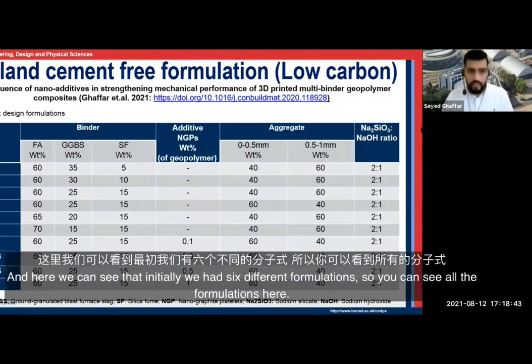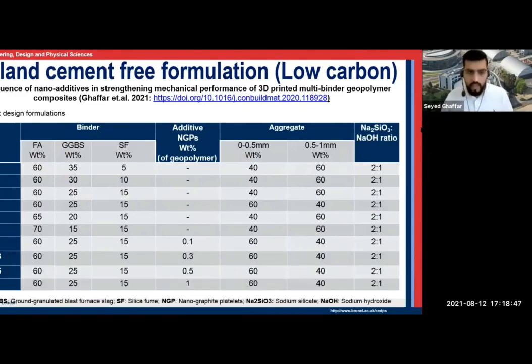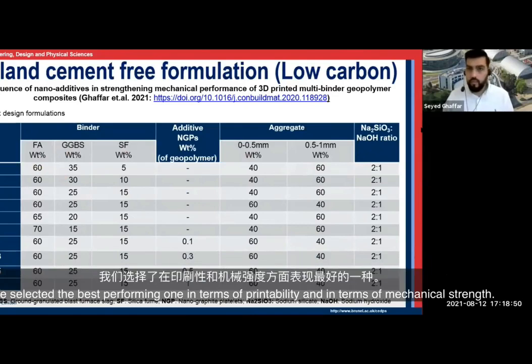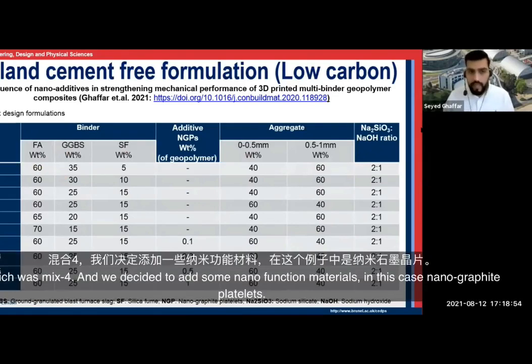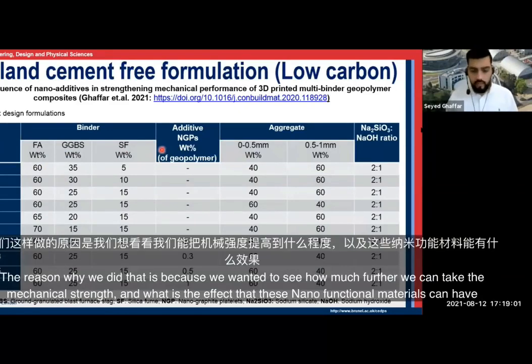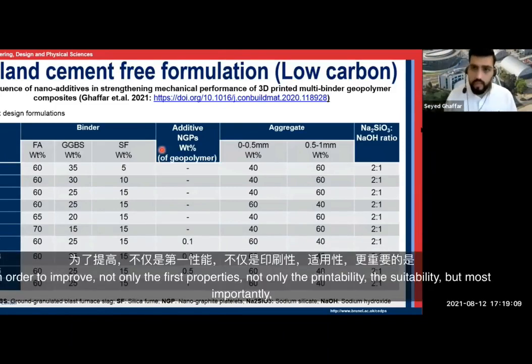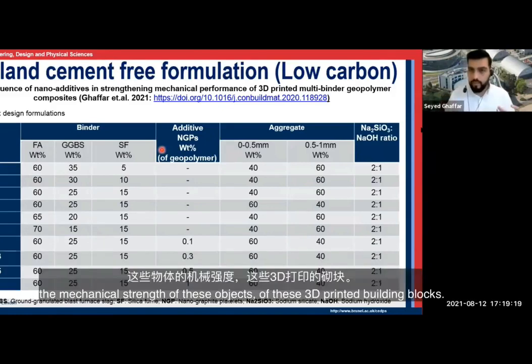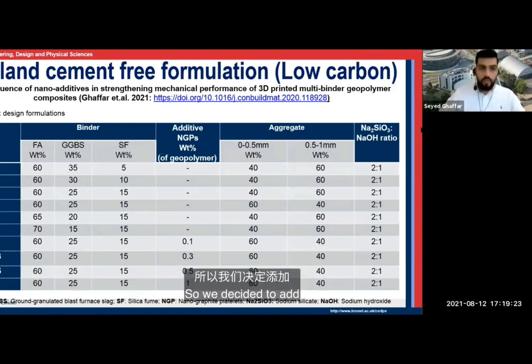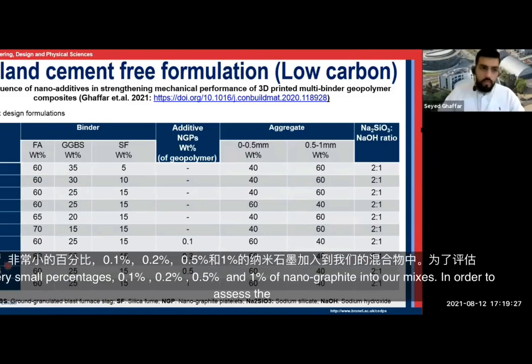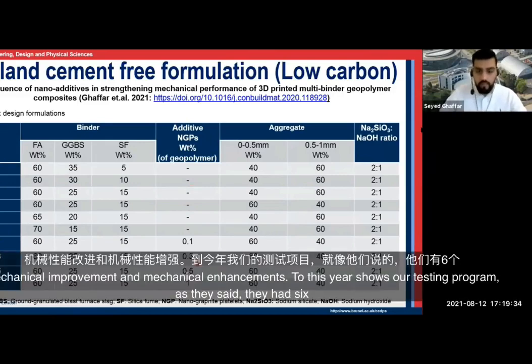And here we can see that initially we had 6 different mix formulations. You can see all the mix formulations here. We selected the best performing one in terms of printability and in terms of mechanical strength, which was mix 4. And we decided to add some nano functional materials, in this case, nanographite platelets. The reason why we did that is because we wanted to see how much further we can take the mechanical strength and what effect these nano functional materials can have in order to improve not only the fresh properties, the printability, the extrudability, but most importantly, the mechanical strength of these 3D printed building blocks. So we decided to add very small percentages, 0.1, 0.3, 0.5, and 1% of nanographite into our mixes in order to assess the mechanical enhancement.